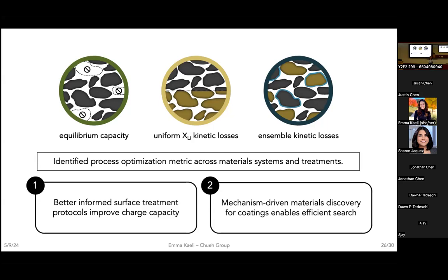Yeah, so the LFP case is interesting just because it's a phase change material, and then you have to consider the strain across the interface between the two phases. I think that's what's largely attributed to the hysteresis between charge and discharge, even at slow currents. But it will affect things. One thing I always yell from the rooftops is that even in a phase change material, the width of your plateau, no matter how slow you're going, is still going to be impacted by the fact that you have multiple particles in your system. So the mixed voltage of that system is going to really impact the plateau width. You might have more capacity you could have extracted from that plateau, but you might have some particles charging ahead because you're not exactly at equilibrium.